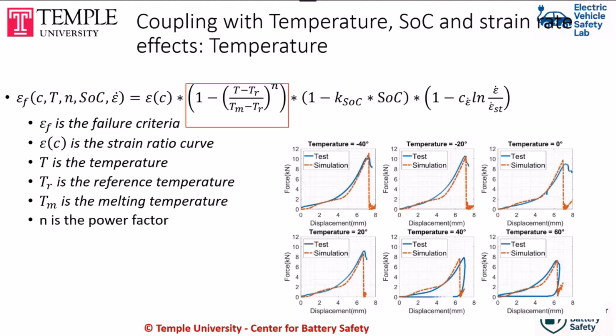And I have different papers, which are out of the scope of today, that show that failure strain should be dependent on the temperature, should be dependent on the strain rate, and should be dependent on SOC. So we have added these features to the main failure criteria to make it valid for when the temperature is different.